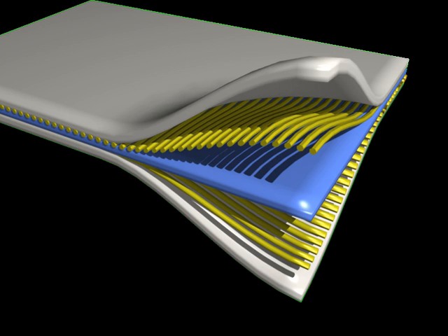Intermediate angles of misorientation theta lead to matrix shear failure. Again, the cross-sectional area is modified, but since shear stress is now the driving force for failure, the area of the matrix parallel to the fibers is of interest, increasing by a factor of 1/sin theta. Similarly, the force parallel to this area again decreases, F cos theta, leading to a total tensile strength of tau_m/(sin theta cos theta), where tau_m is the matrix shear strength.